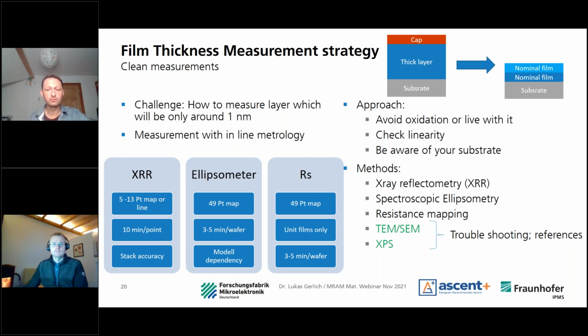Normally we use X-ray reflectometry, spectroscopic ellipsometry, and resistance mapping, for example. Each of them has its own advantages and disadvantages. Reflectometry takes long to measure, but you have a very high stack accuracy. For ellipsometry, you can make nice maps. It's quite fast, but it depends on the model you use, so you have to develop quite an elaborate model for each stack. Resistance measurement is quite fast. You can also make maps, but it can measure only single films. And of course, the resistivity is dependent on the thickness in these ranges, but sometimes that's exactly what you want to know. And for sure, other methods for troubleshooting and references, like electron microscopy or X-ray photoelectron spectroscopy, are also possible.